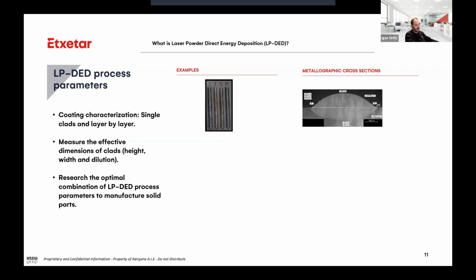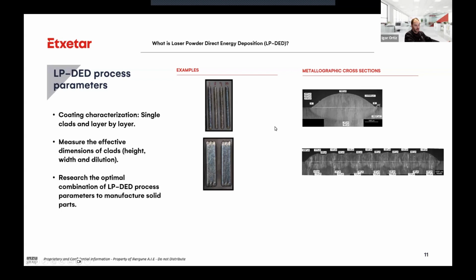How do we do our research, or how do we characterize the process? We start with simple tracks, selecting a specific powder. In this case, we have selected Dievar material for repairing the ring gear. We do different tracks with different process parameters. We check each track in the metallographic laboratory for porosity, lack of fusion, or any issues in the quality of the tracks. When we have the height and the width of the track, we select one track and the process parameters that are linked, and we launch one layer coating and